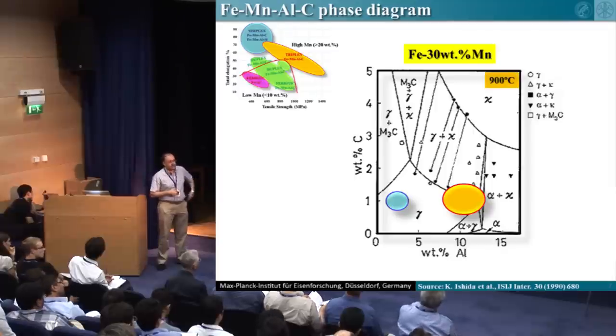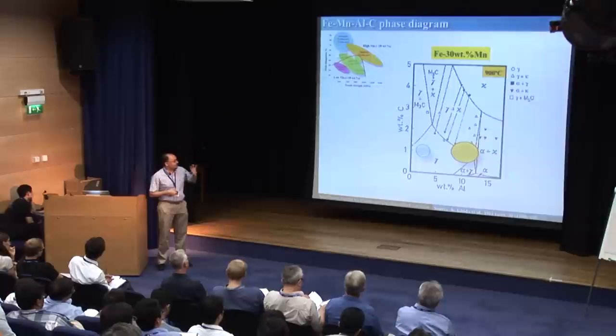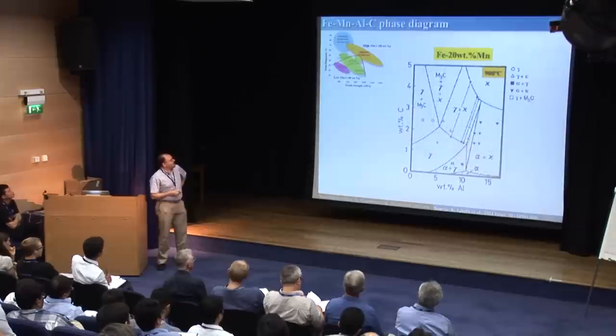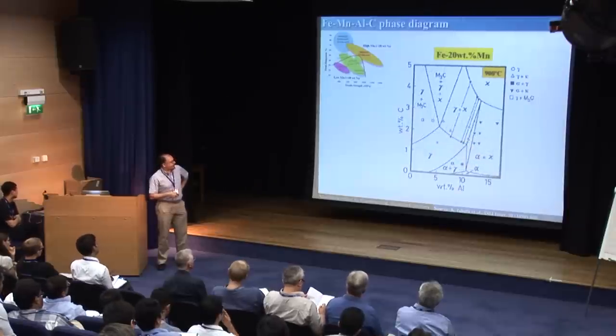So it's mainly controlling the damage mechanisms, basically. So in the triplex today, I will just concentrate on the austenite and kappa. As you can see here, we reduce the amount of manganese. Basically, the ferrite is much more stable. And this is what we have in these steel grades here.